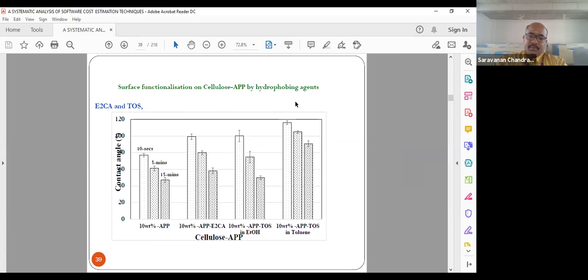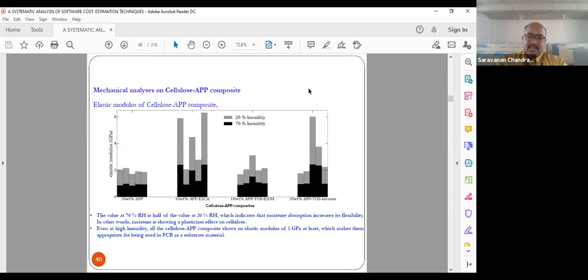So when you go for ammonium polyphosphate, we used the dip coating method. In the dip coating method, we tried two different solvents, ethanol and toluene. Toluene is the more suitable solvent, because ethanol also has a hydroxyl group with which the hydrophobic agent interacts, which avoids more coating on the surface, giving a lower contact angle when you compare with that.